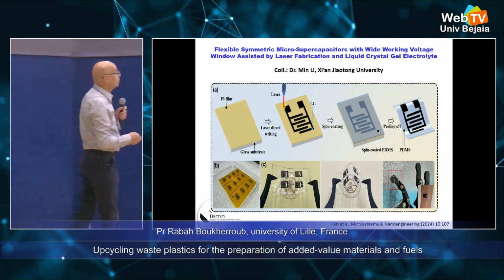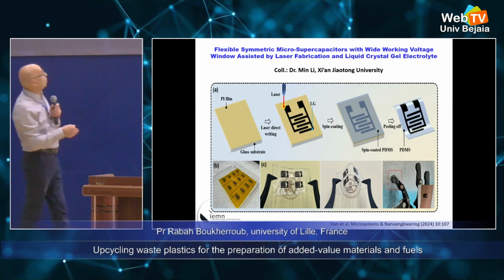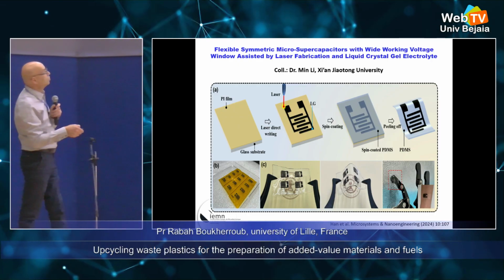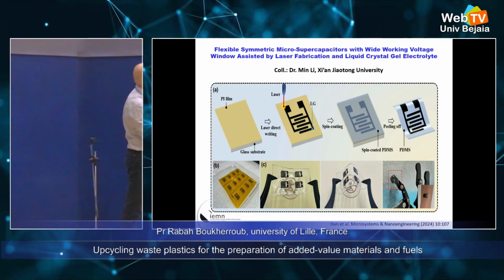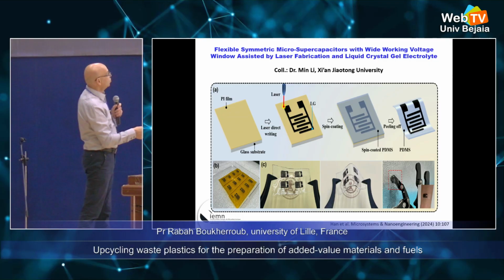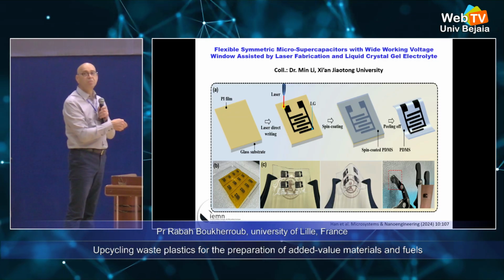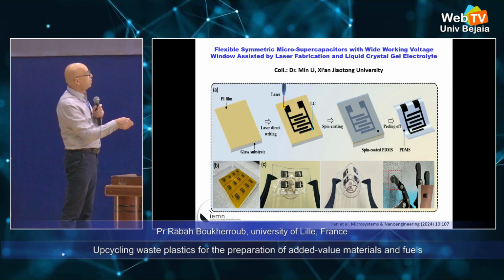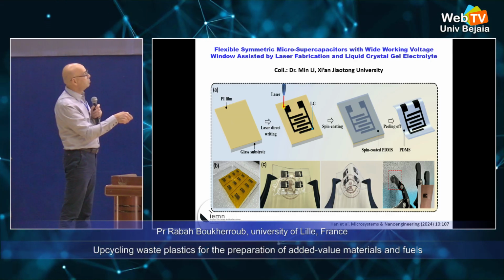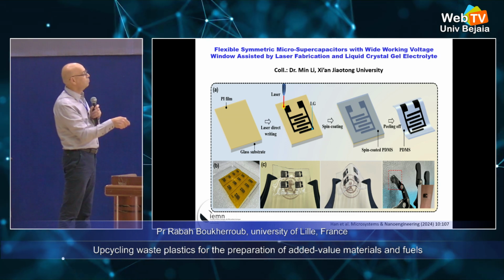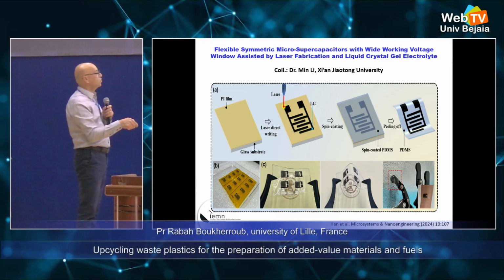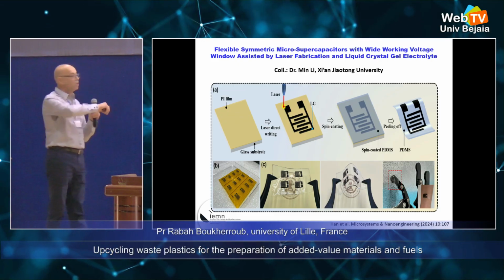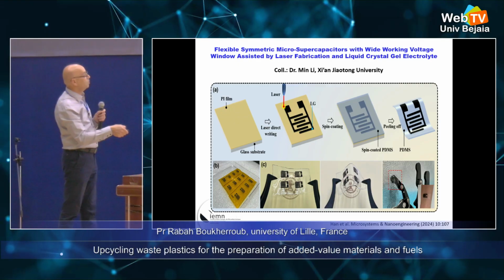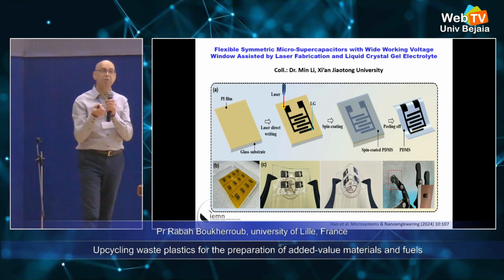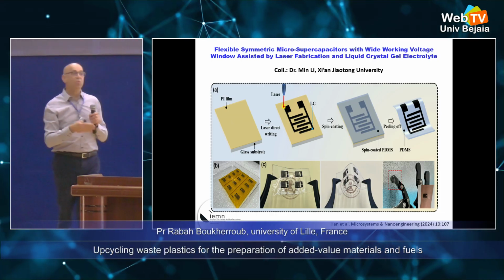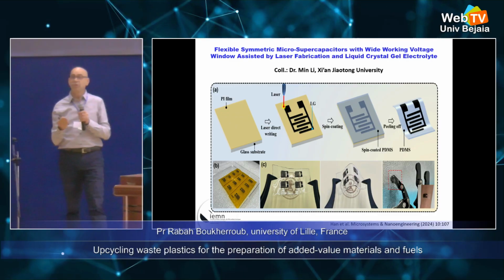It's very easy. So the first thing we did, this is Dr. Min Li, who is my former PhD student, now an associate professor in China. So she took glass, you have a polyimide film. Just with a laser, you can pattern very easily. You see, you transform the polyimide to graphene. It's black, it's a graphene type. Then we just coat with a spin coating of a thin film of PDMS, peel off. Then you transfer this pattern to the PDMS. Now you have a flexible electrode material, okay?